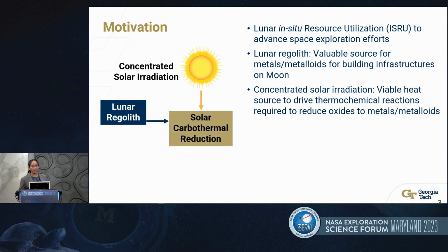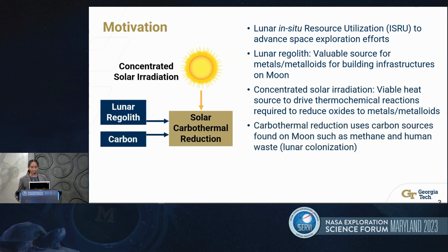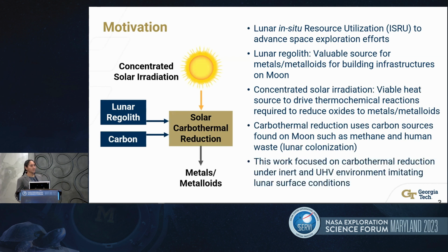One such pathway is solar carbothermal reduction, which is the focus of this work. This pathway requires carbon as a reductant, with the benefit of reducing the reaction onset temperatures as compared to direct thermal heating. And carbon can be found on the Moon in the form of methane or human waste upon colonization. This work specifically focuses on this pathway in inert and ultra-high vacuum conditions to imitate lunar surface conditions to extract metals or metalloids.